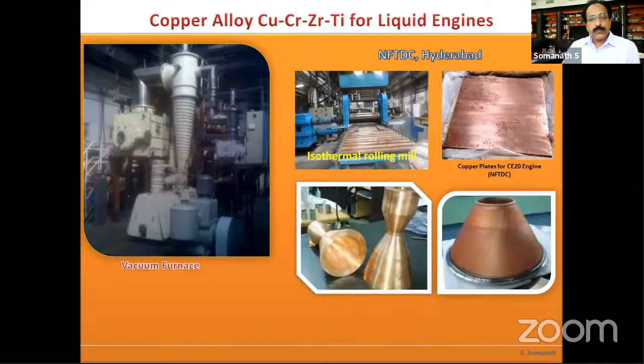Another important development was copper alloys for liquid engines, where the forming of this copper is very, very critical, and also under different cycles of temperature, the accumulated plastic strains had to be limited. So these copper plates were alloyed and formed in some of the Indian facilities, and they have been successfully used in the cryogenic engine program, where thrust chambers with narrow chemically milled cavities and brazing have been successfully used with stainless steel for manufacturing of these engines.